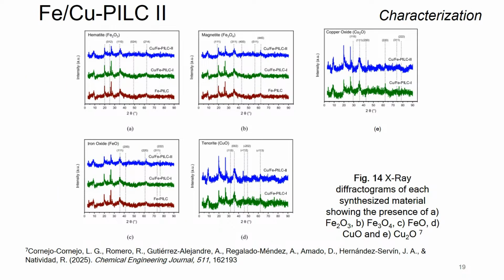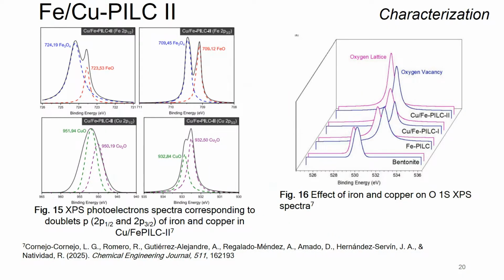We observe all this mixture of phases: ferrous, ferric, magnetite, and cuprous and cupric. Very important, and there is something that usually from the point of view of photocatalysis we don't study, and that is the oxygen vacancies. Yes, there are studies related to that, but it's not standardized in the photocatalysis area. But well, we observe here, and please pay attention to this, the higher the content of copper, the higher the oxygen vacancy. And then you later will be able to correlate that with the production of formic acid.